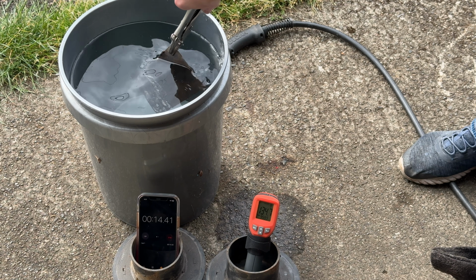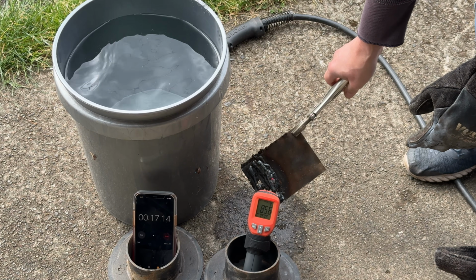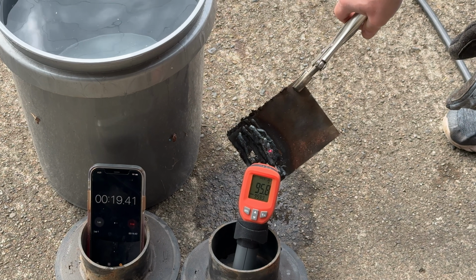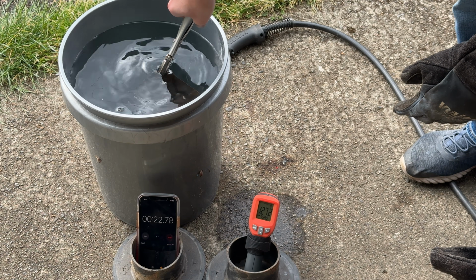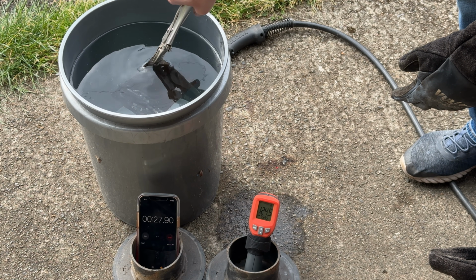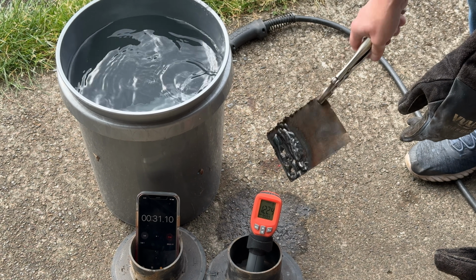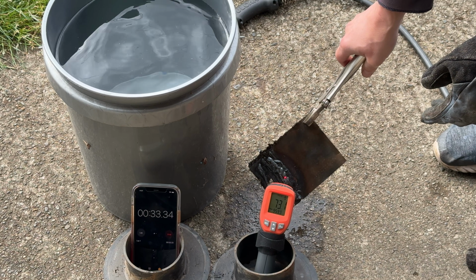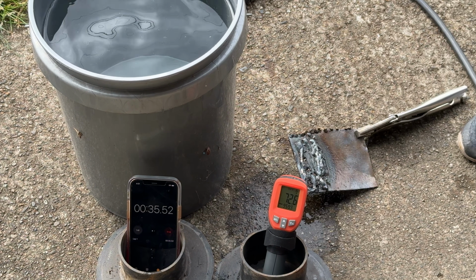I pulled the test panel out of the water at the 15-second mark, and it was still roughly at 96 degrees. So I dunked it back in for another 10 to 15 seconds, and right at the 30-second mark, we were at our target temperature of 73 degrees. Well, the results speak for themselves. Water cooling is just so much faster and more efficient.